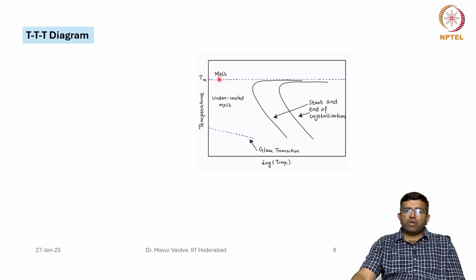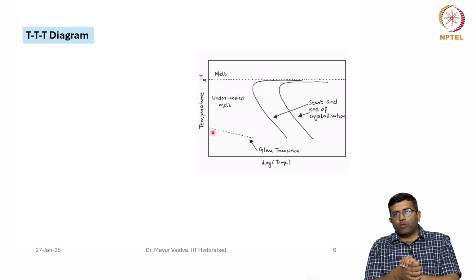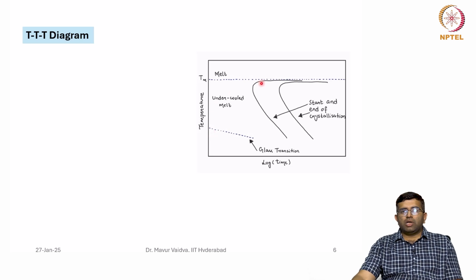If you start bringing down a melt below its melting point, it requires a certain time for the crystallization to occur. This curve represents the start of the crystallization and this represents the end of the crystallization. That means if you bring down your melt to a temperature here and hold it, it will require this much time for the crystallization to occur. That is because the crystallization happens through nucleation and growth. The rate of crystallization is maximum at an intermediate temperature, not at the melting point nor at very low temperature.